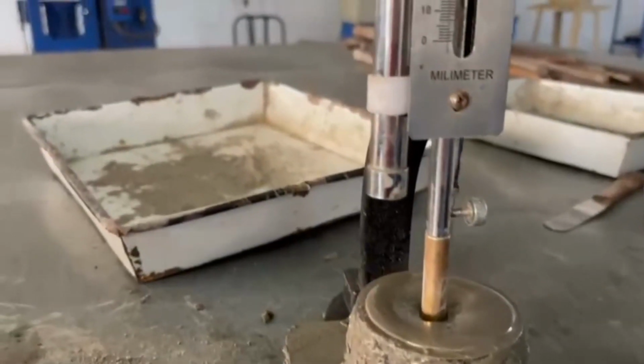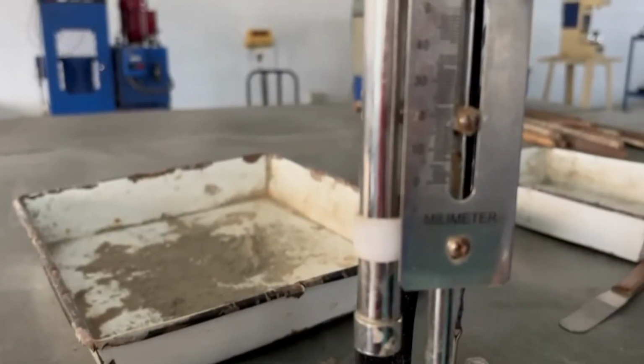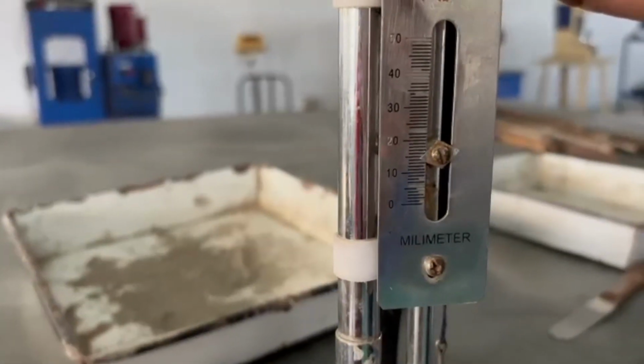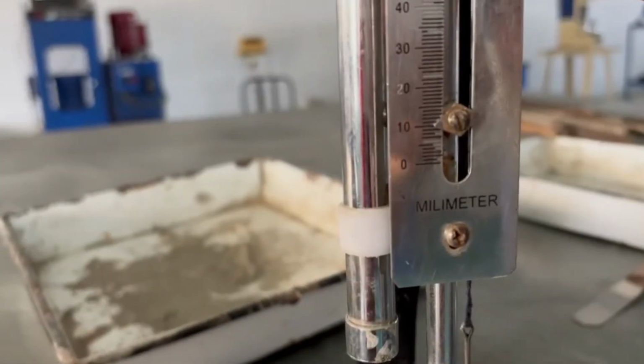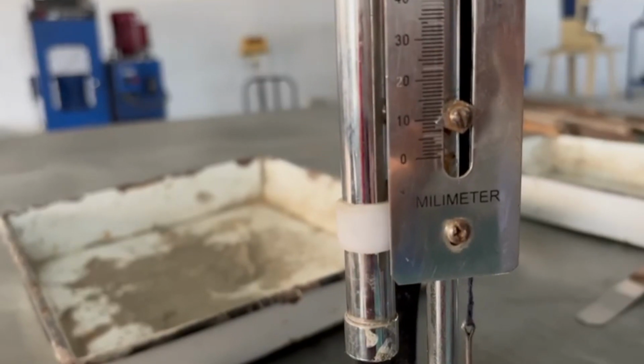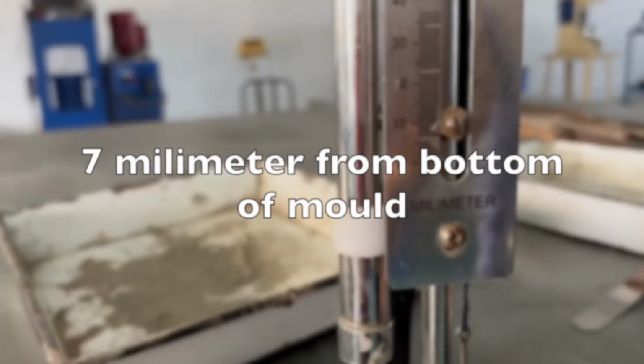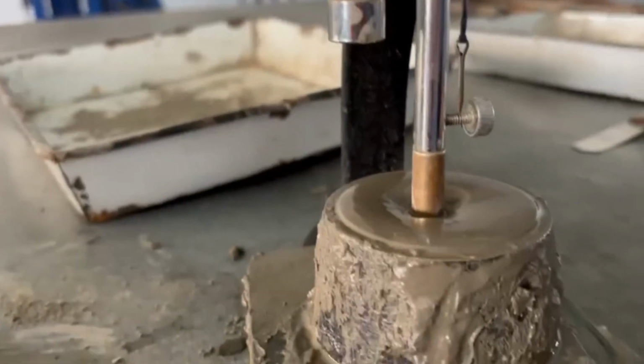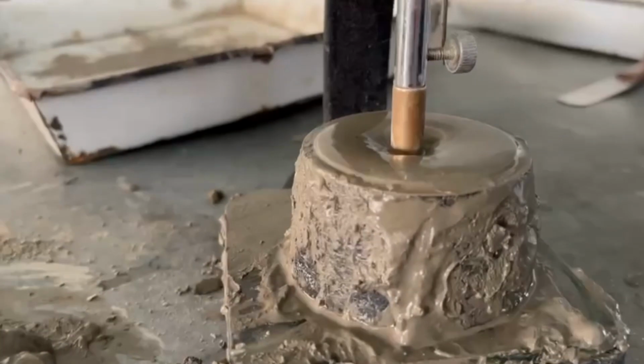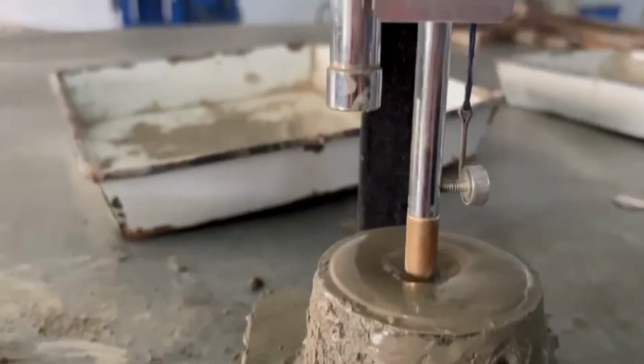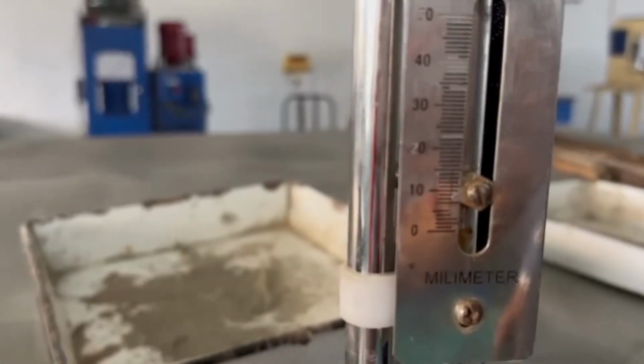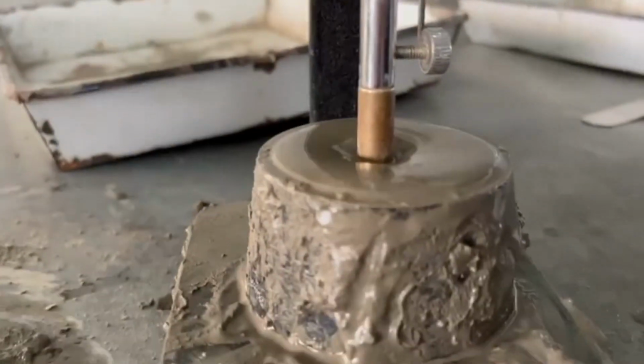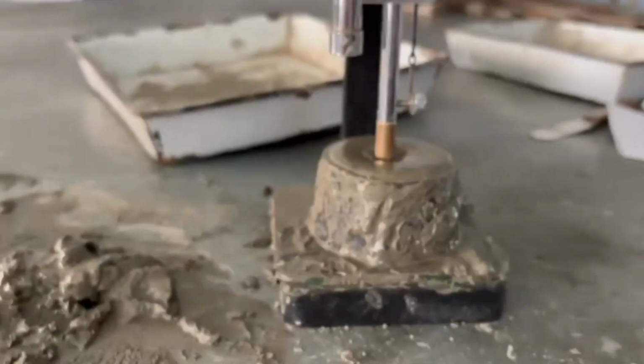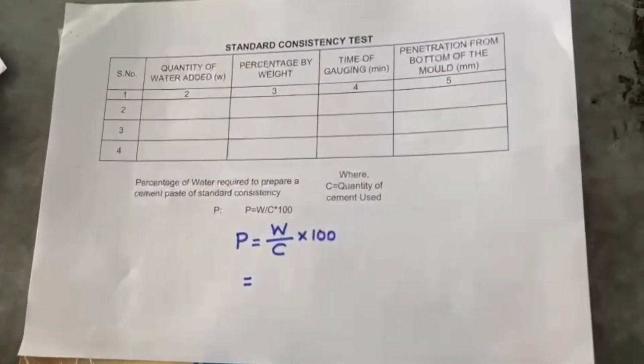Now you can see the penetration is near 6, 7. This is our requirement, 5 to 7 millimeter. You can see this indicator is at 7 millimeter. So it indicates our normal consistency: water to mix at the ratio of 34% by weight of cement. This data you can record on your list. So you can now enter the data that you have recorded.